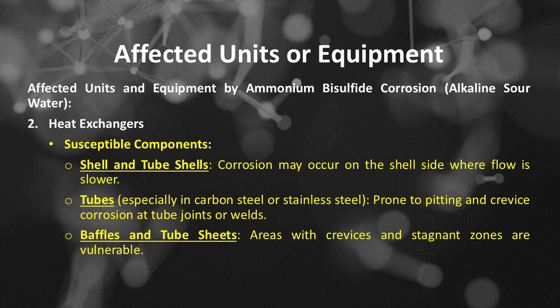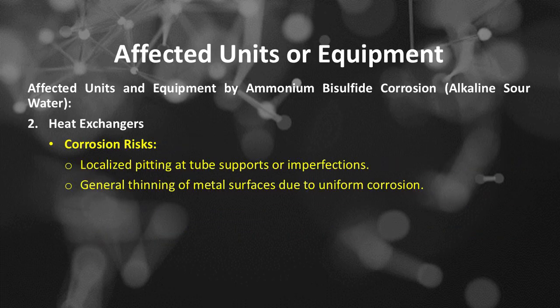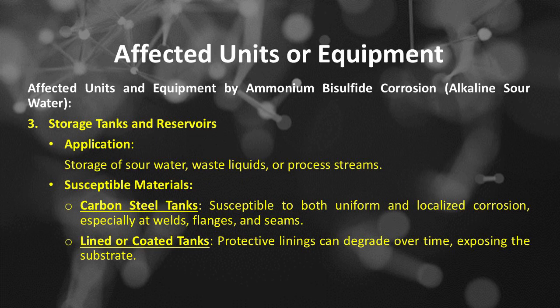Tubes, especially in carbon steel or stainless steel, are prone to pitting and crevice corrosion at tube joints or welds. Baffles and tube sheets, areas with crevices and stagnant zones, are vulnerable. The corrosion risks of heat exchangers include localized pitting at tube supports or imperfections, and general thinning of metal surfaces due to uniform corrosion.